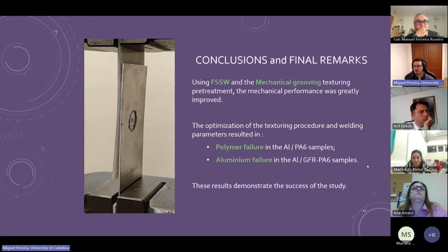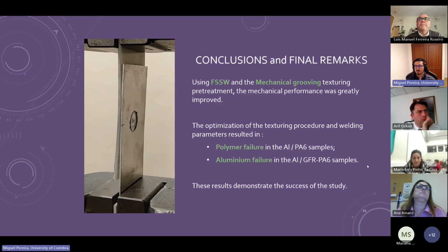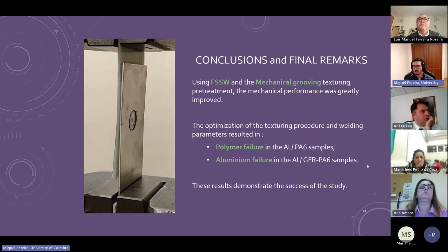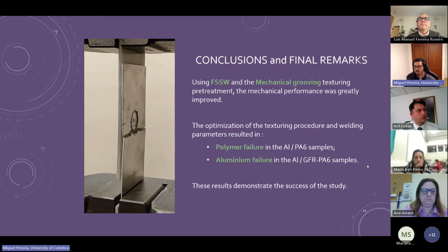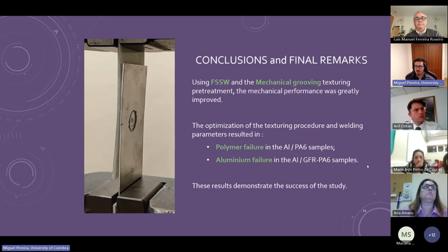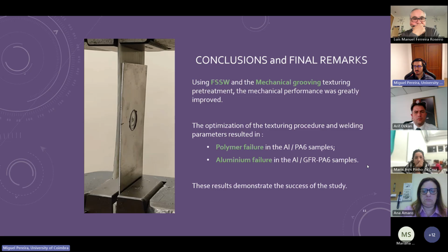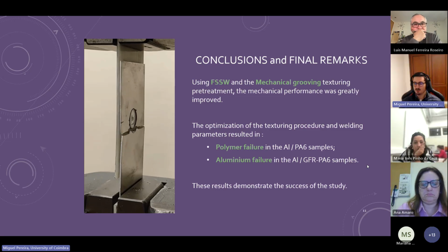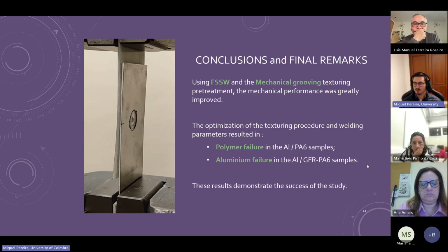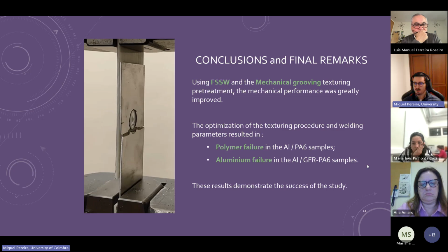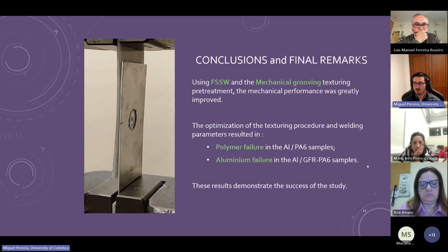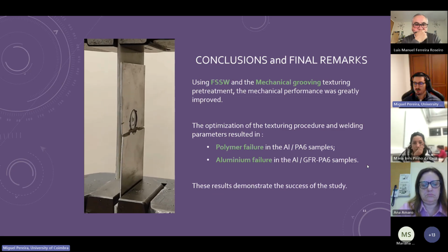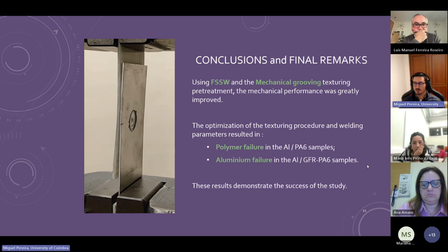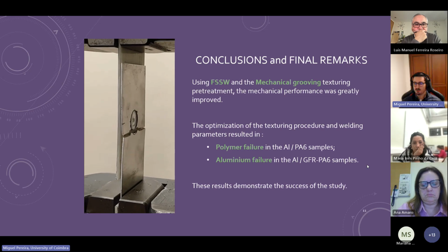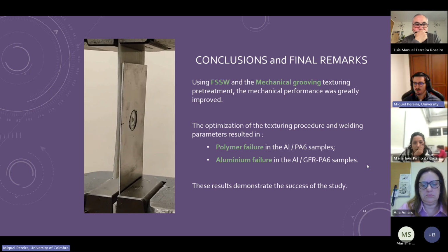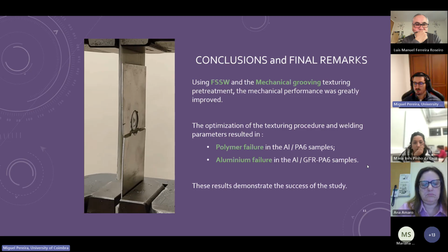So the conclusion is that using the friction stir spot welding and the mechanical grooving texturing pretreatment, the mechanical performance was greatly improved, and that the optimization of the texturing procedure and the welding parameters resulted in the case of aluminum polymer samples in polymer failure, and then as illustrated in this video, in the aluminum composite samples in aluminum failure. So we consider that these results demonstrate the success of our study.